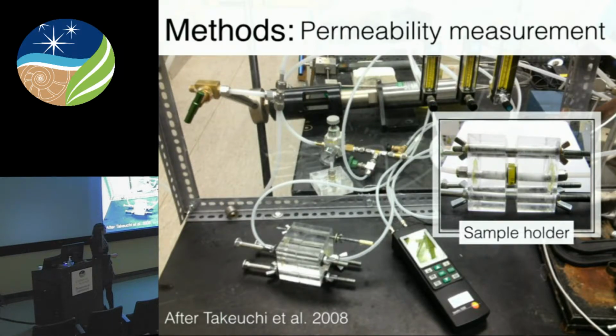So what we do is we force compressed air through the sample and measure the pressure differential upstream and downstream of the sample over a range of gas flow rates, and we use that data to then calculate permeability using a modified version of Darcy's law.